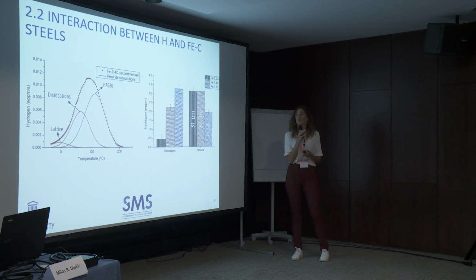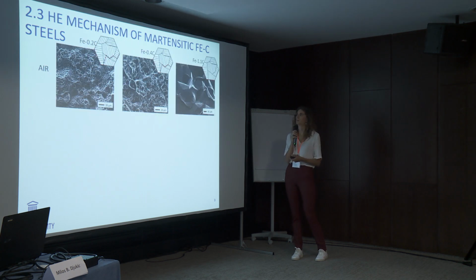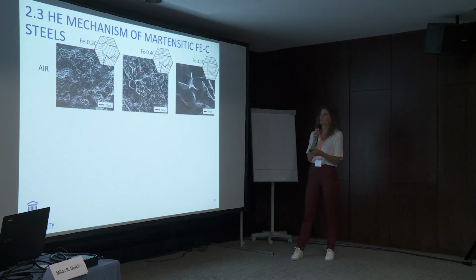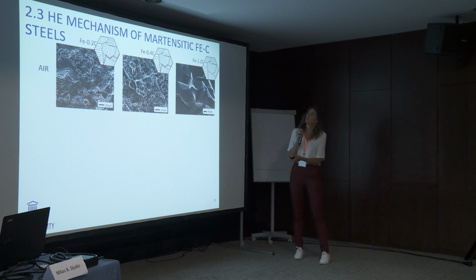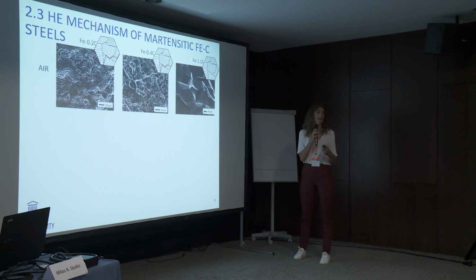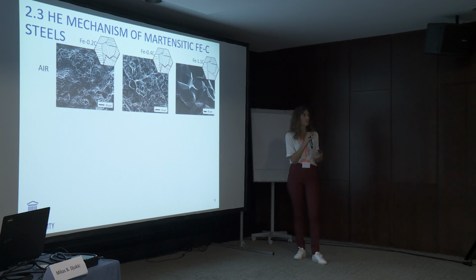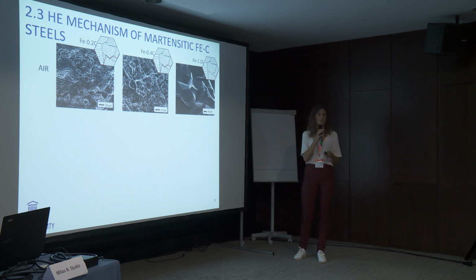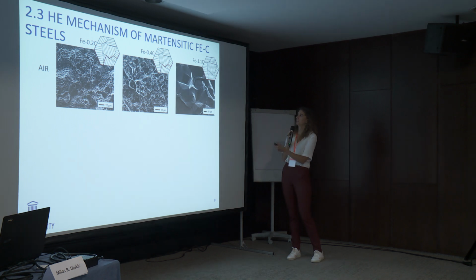So now we know where hydrogen is trapped in this type of steels, and we can look at the mechanical behavior. So these are the fracture surfaces which are obtained after bending tests in air. So with 0.2 weight percentage of carbon, we have a fracture surface which mainly consists out of microvoids. For the 0.4 carbon steel, we have a mixed fracture surface. We have some intergranular features, microvoids, and cleavage facets. So it's really a type of mixture. And for the 1.1 carbon steel, we have a purely intergranular fracture surface.